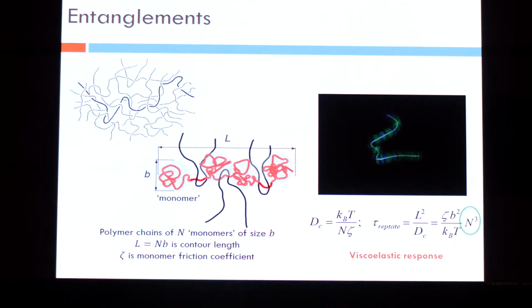Now, one of the key things that we need to understand, this is 101 on polymer topology, keep it very simple. These polymers, if you were to zoom in and look at these individual polymers in the polymer melt, you will see that they look like a mass of noodles. You have these long chains embedded into many other long chains. So they are what we call entangled into each other, like a cotton candy. And these entanglements are very, very critical to the flow properties of these materials.